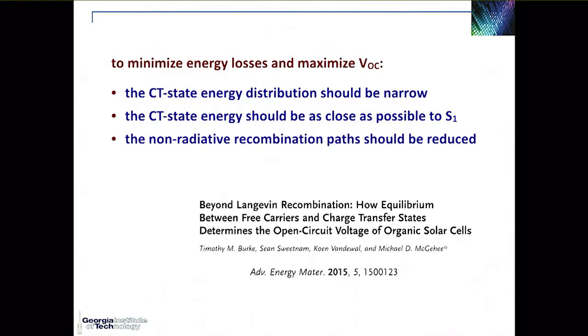The lower CT state energy should also be as close as possible to the S1 energy. And then you also need to minimize all the non-radiative recombination pathways that would lead from the CT state back to the ground state, for instance, which means loss of a photon.